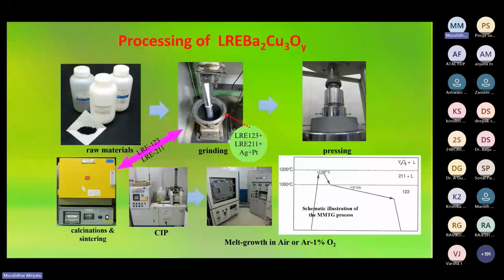So you have to mix the powders, press, sinter, and slow cool below 1000 degrees centigrade. It is very, very slow, 1 degree centigrade per hour, like 100 hours. Eventually we have to oxygenate at 400 to 450 degrees for around 600 hours, depending on how long. Even if the samples are larger, we have to go several days. Otherwise, 200 hours is enough to make the superconductor. Then we successfully produced high quality bulk superconducting magnets in the world.